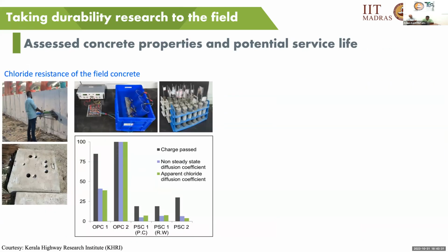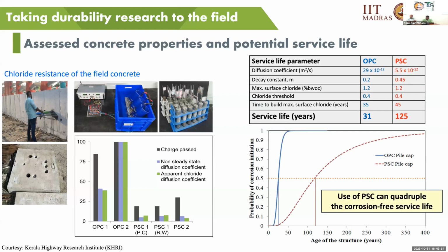To really implement it, first we had to convince them that this concrete is actually useful. So we cast specimens on site and tested concrete specimens collected from the actual structure. We found that the durability of such concretes can be very, very high compared to the OPC concrete. We also looked at service life estimates, and found that by using the slag concrete, the service life can be about 4 times more than the OPC-based concrete. This was very promising, and they were very happy. And now, we know that they are implementing this type of concrete in other bridge projects as well.